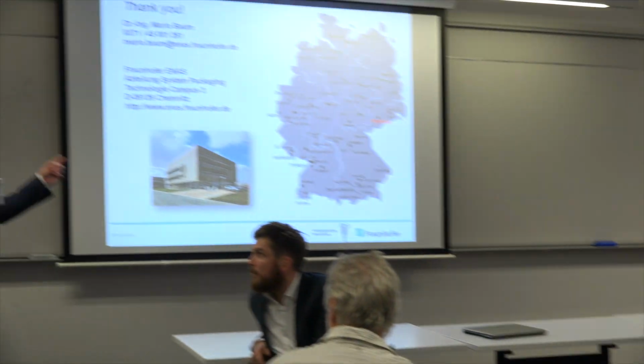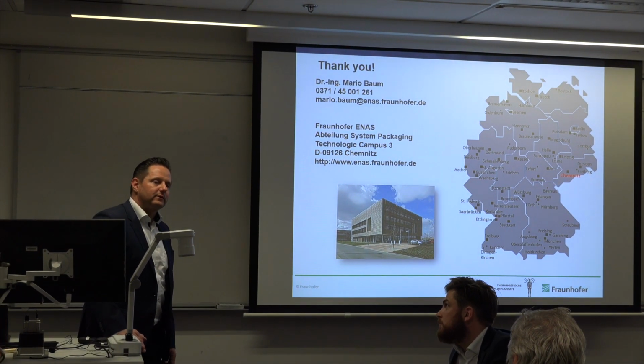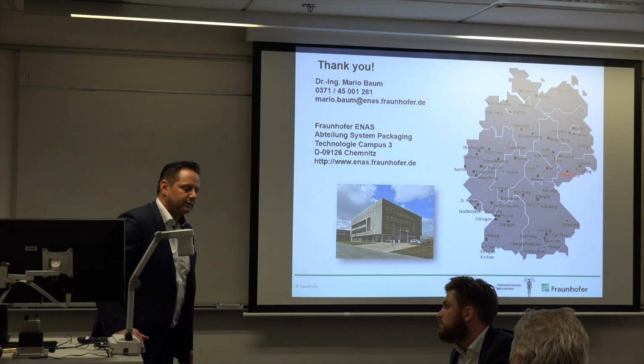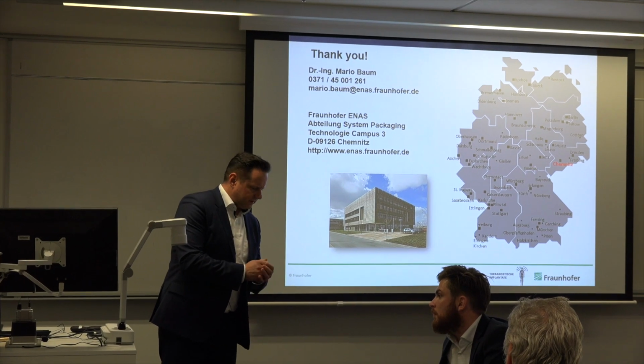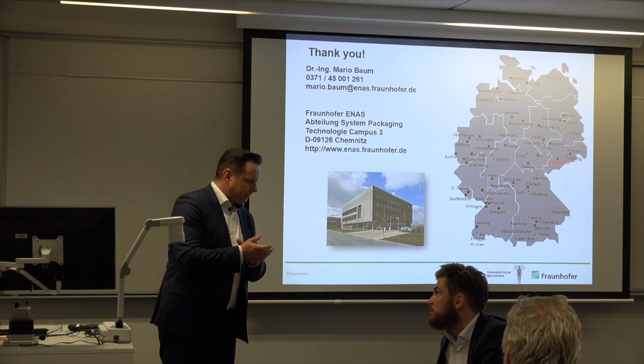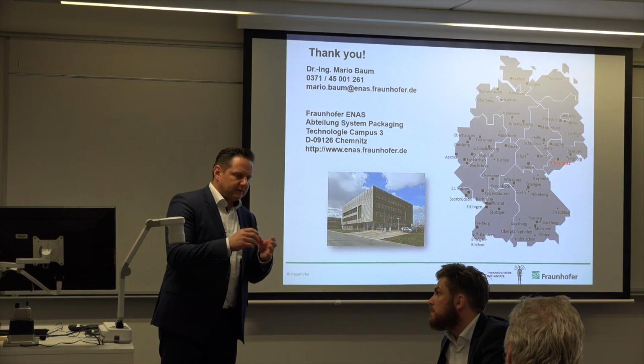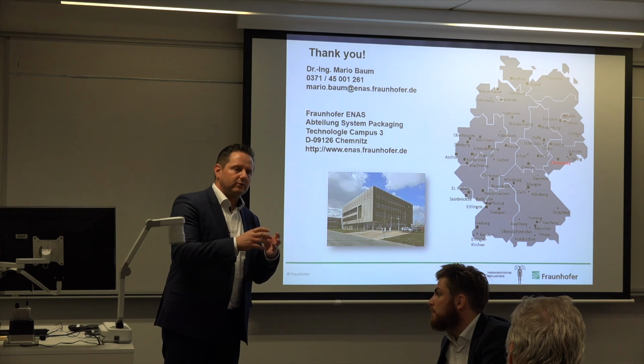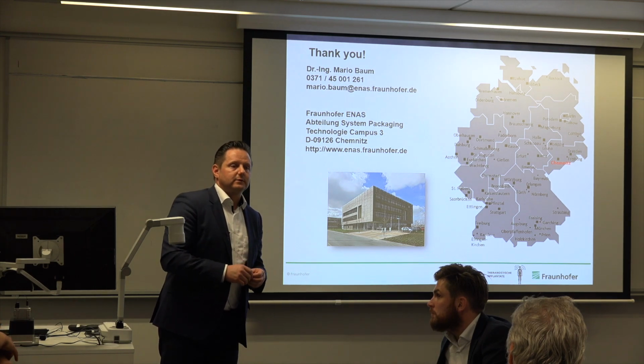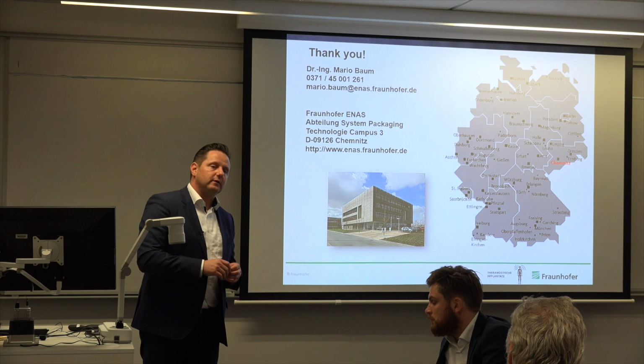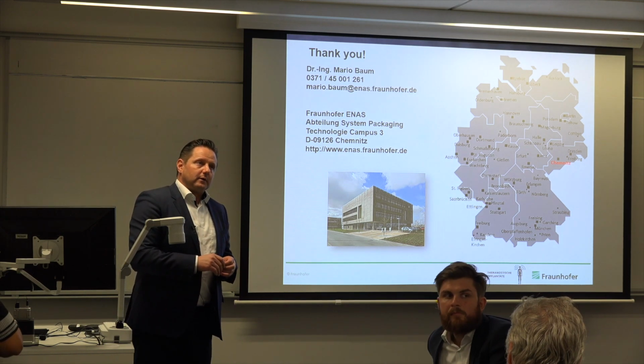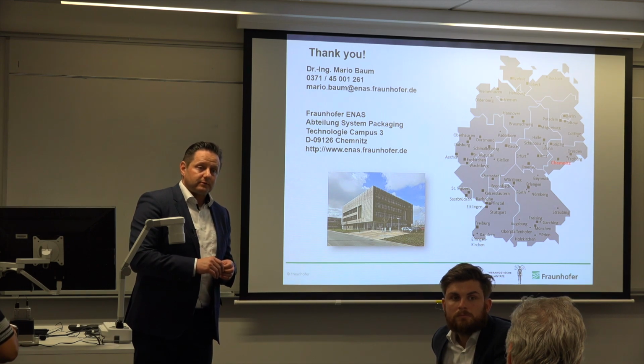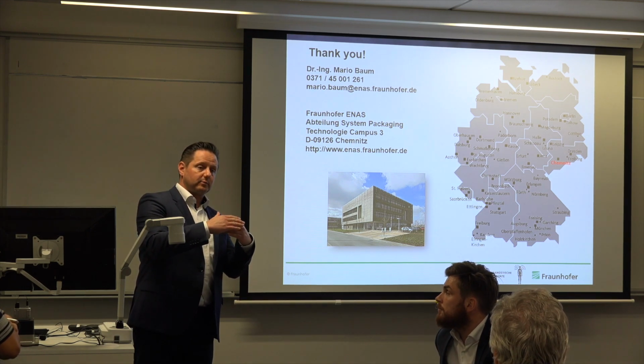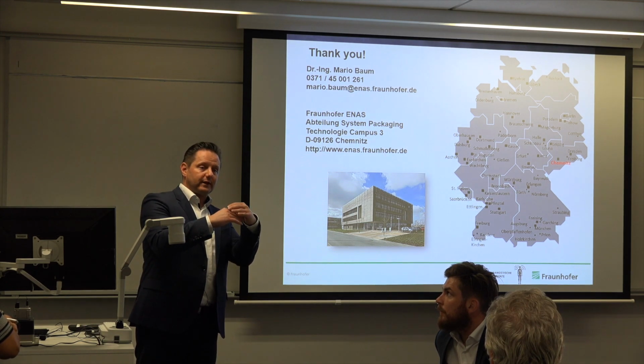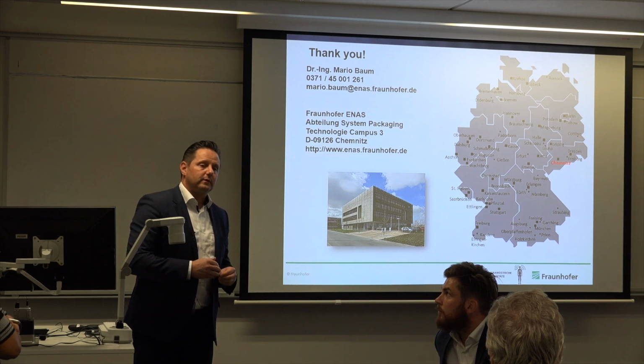So we did not test the whole system with a layer combination, but we had a test setup by using a so-called calcium test. I think it's a kind of hermetic sealing test where you have calcium, and the reaction under oxygen or humidity is simply detected by color change. And so we use this parylene in combination with a thin film layer of aluminum oxide deposited by atomic layer deposition, ALD, and then we have this kind of sandwich structure of parylene, ALD, and parylene to protect this thin, 50 nanometer thin aluminum oxide layer.